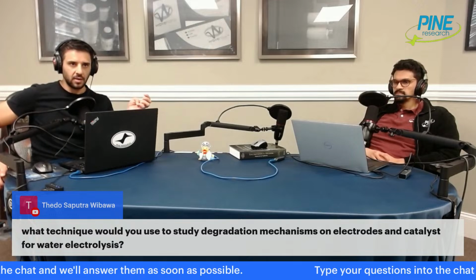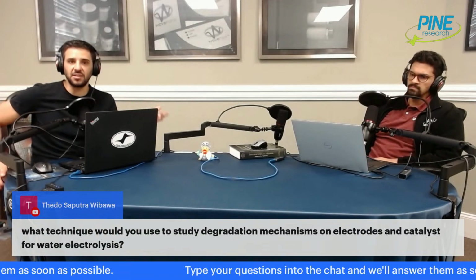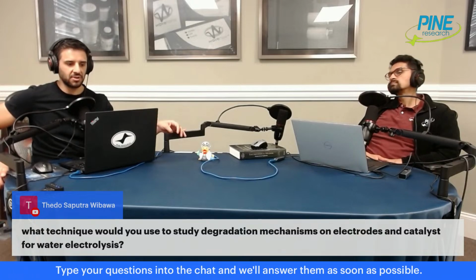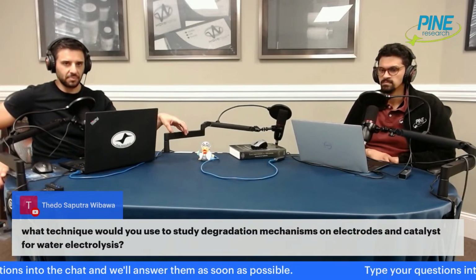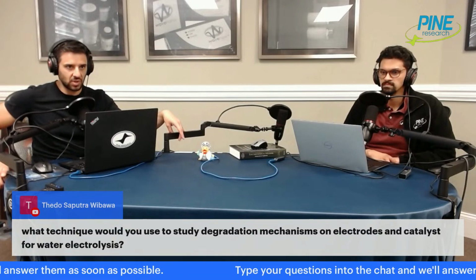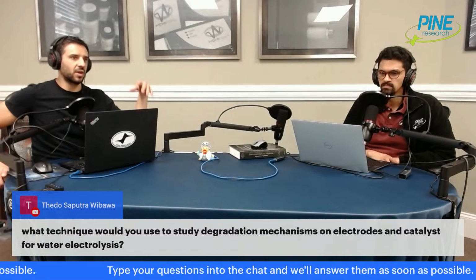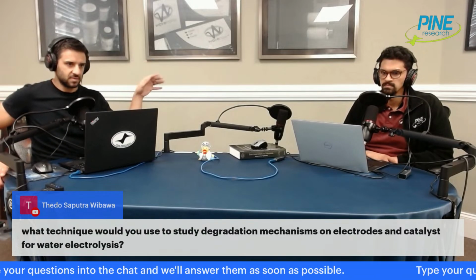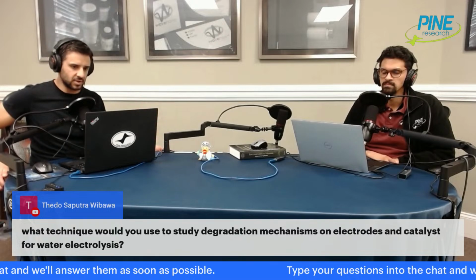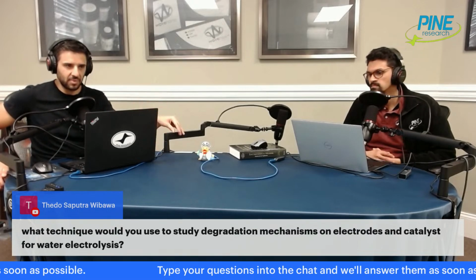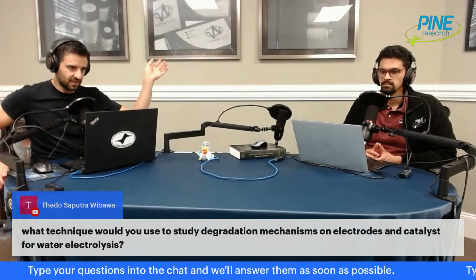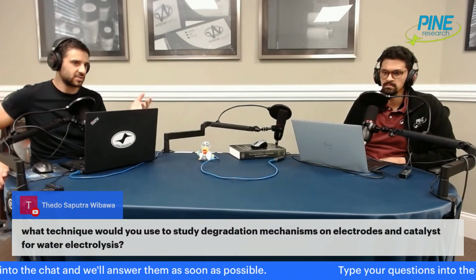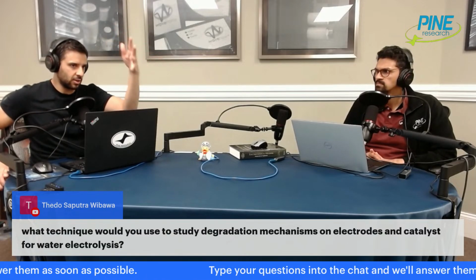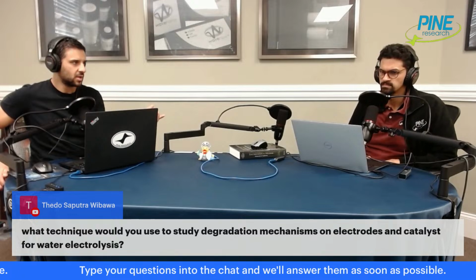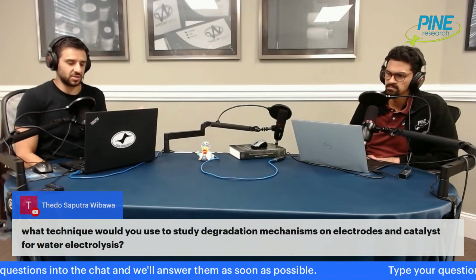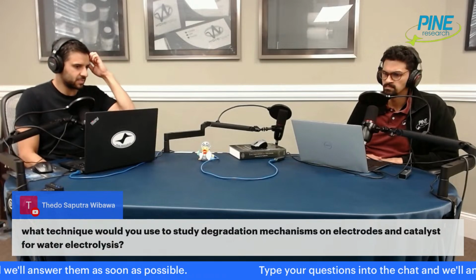And so one kind of answer you could have, for instance, to study the degradation of your electrode would be something like, how does the overpotential change with time for the same electrode, right? Okay, well, I do OER, 1,000 cycles over 2 weeks or something. I'm just making up numbers here, right? But it's like, okay, well, the overpotential was only like 50 millivolts in the beginning, and by the end of 1,000 cycles, the overpotential increased to 200 millivolts. So there's some degradation because the overpotential is worse. That's one metric. So that's like a sweep technique.